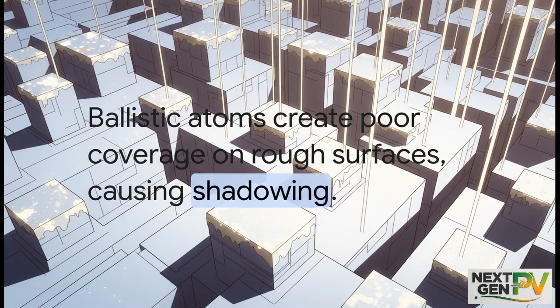Remember earlier when we said the atoms travel in straight ballistic lines? That causes a major issue called the shadowing effect, which leads to poor step coverage. If your substrate has tiny microscopic trenches, walls, or rough textures, the vapor atoms will hit the top ridges but be physically blocked from reaching the valleys below. It's exactly like how standing right behind a tall building blocks the sunlight. Also, it's incredibly difficult to evaporate materials that have extremely high melting points, like tungsten, at least unless you upgrade to a really expensive electron beam system.